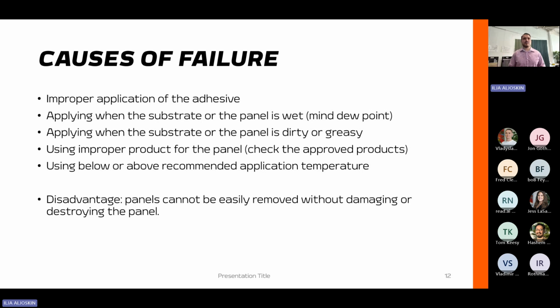So when speaking with the manufacturer, they've done over 1,000 projects all over the world, and through those projects they had several failures, and all those failures were attributed to improper application. There were only a few failures, and they could track it back to some kind of improper application, which could be that the substrate was wet because it was early in the morning and there was dew on the aluminum or something that you needed to attach to. And when the substrate or the panels are wet, the adhesive doesn't work as well. Maybe the substrate was dirty or greasy and the panels weren't cleaned correctly. Using an improper product for the panel.